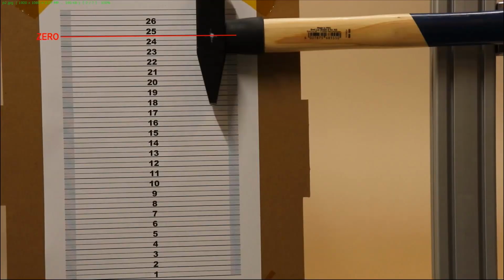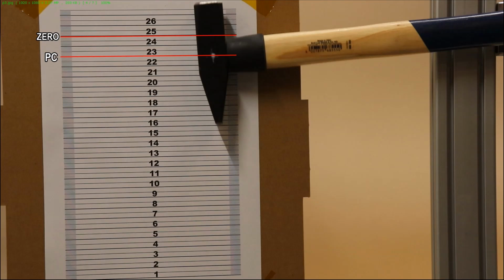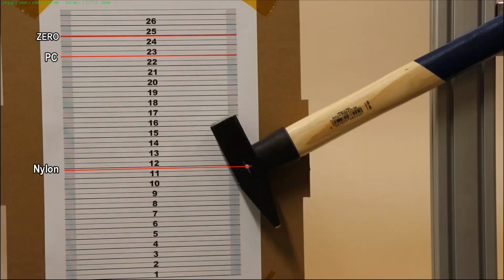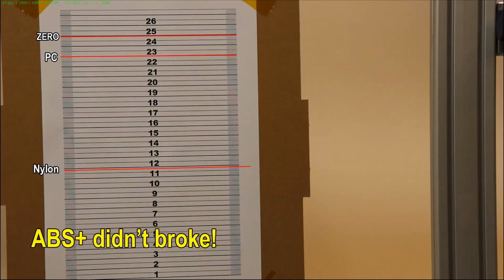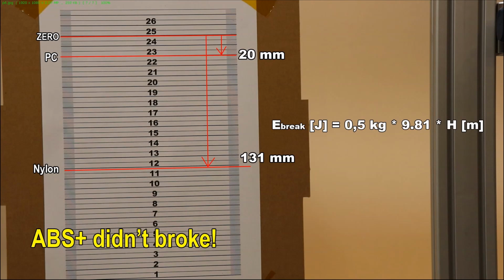So this is the scale, and this is the 0 position of the hammer. And this is the position of the hammer after breaking the PC test specimen. And this is after breaking the nylon. And just to remind us, the ABS Plus didn't break at all. And if I measure everything from the 0 position, with this equation I can calculate the breaking energy.